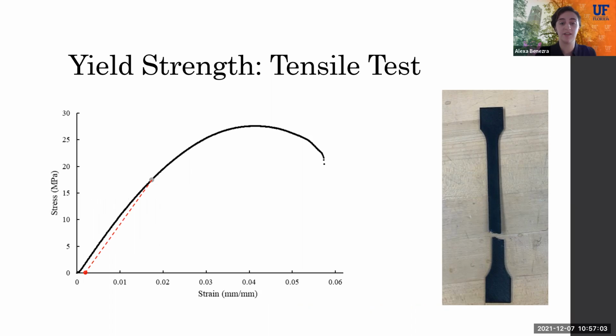The tensile test that we performed on the printed specimen is not directly translatable to the print of our actual housing due to the orientation of the threads in the printing. Even though the infill was the same, the threads on the test specimen were created perpendicular to the threads on the housing. But we chose to perform a tensile test on the material in the housing because during one of our design iterations, the housing collar experienced a tensile failure, which will be explored in the next few slides.